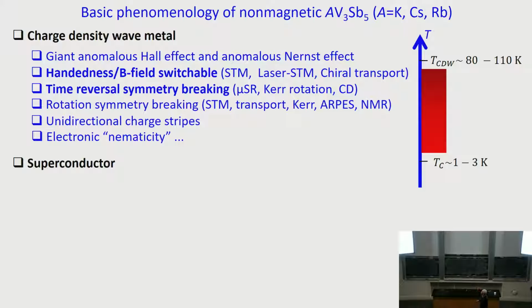There is a whole other phenomena related to rotation symmetry breaking. It turns out the six-fold symmetry of this hexagonal material is broken, and there is unidirectional charge stripe ordering, and there is also electronic nematicity at very low temperatures. Many of the high Tc phenomenology you'll see here as well. So if the normal state is so anomalous, you know the superconducting state is going to be very strange or very interesting. First of all, the superconductivity coexists with charge density wave order.